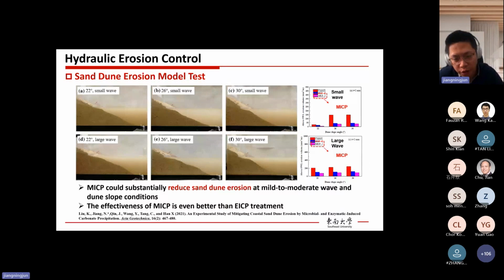Okay, so in addition to internal erosion control, we also looked at sand dune erosion under different wave conditions. Here is a very simple model test in the laboratory. We made sand dune models at different angles from 22 degrees to 30 degrees, and we made waves with different magnitudes, small waves and large waves. In this test, we used the erosion volume to see how MICP could help to mitigate erosion.